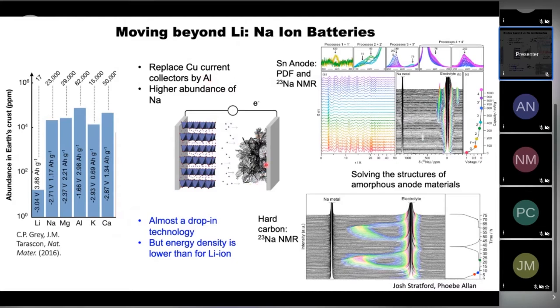And so instead, people have proposed these hard carbons, which are amorphous forms of carbon containing graphene or graphite sheets that are a little bit larger in size so that you can still intercalate the sodium ions into them. And by using NMR, we're able to follow the processes that go on. And we can show that the first process on discharge is associated with diamagnetic environments near defects. And then the next process involves the intercalation and the formation of metallic sodium.